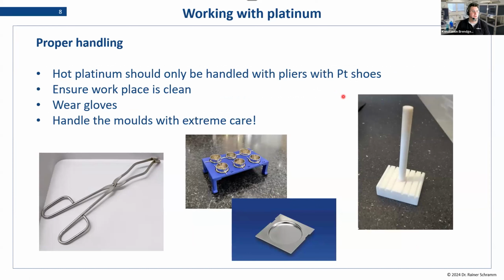Now, on to handling. A few general rules. You only want to touch hot platinum with a plier that has these little platinum shoes. Having hot platinum touch cold metal is generally a bad idea, so avoid it. There is also the rule that you want to make sure that your workplace is clean. Beware of dusts; they can cause problems. Wearing gloves is recommended, and especially with the casting molds, you want to be extremely careful when handling because of the polishing in the middle. They are finished with a special polishing, and each scratch, which can be caused by uncareful handling, can cause problems later, and might lead to an early recycling being necessary because they just don't work anymore.